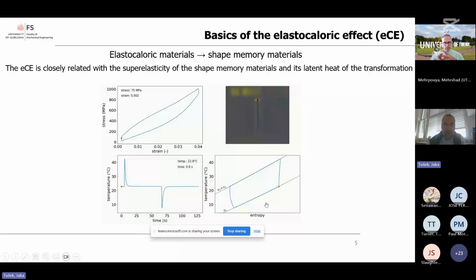So the first step in the cycle is mechanical loading, so the material transforms from austenitic to martensitic phase. Because this is done at close to adiabatic conditions, the material heats up, and then it's able to transfer this heat to the surroundings. Upon unloading, the reverse transformation occurs, the material cools down at adiabatic conditions, and this cold material is now able to absorb heat from the surroundings. So if we constantly repeat those 4 basic operational steps, we can build a thermodynamic cycle and essentially a cooling or heating device around this elastocaloric effect.